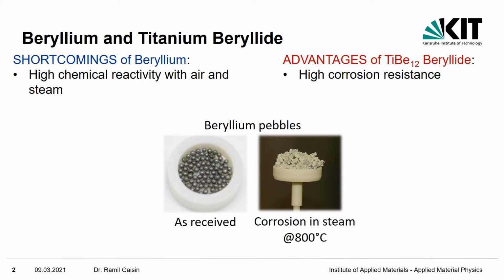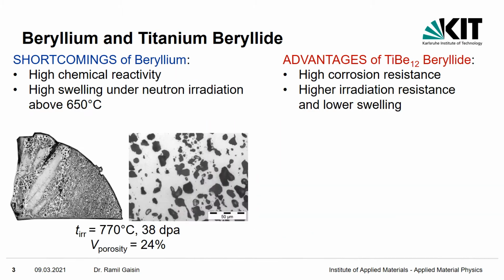For a long time, beryllium was considered the main candidate for neutron multiplication in fusion reactors due to its unique physical properties. However, metallic beryllium reacts strongly with steam and air, as shown here below. Under neutron irradiation, beryllium was intensively forming a very high porosity. But the addition of just one titanium atom to 12 beryllium atoms radically changes the structure and properties.